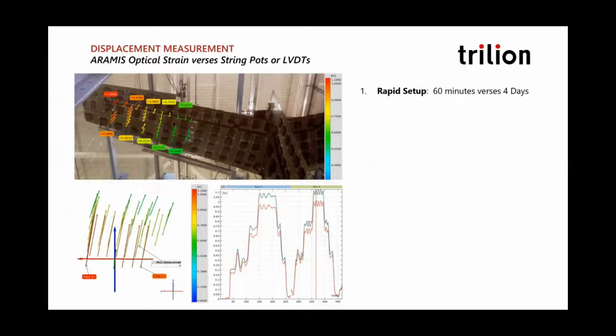String pots are used extensively in the aerospace and automotive industries. The string pot takes a reasonable time to get set up, I mean, literally days, where this patterning, putting target dots up on this wing, just took 60 minutes, including the whole test. And the modelers that we were working with said that the linear data from the string pots is pretty meaningless to them. But the 3D measurement that we're collecting is much more useful in direct model comparisons.